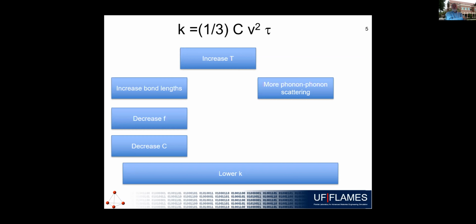Another effect is you have more phonon scattering. That is equivalent to having more people carrying cups of coffee around the room, and they're interacting with each other, so they're effectively all slowed down. When you have more phonon scattering, that's a decrease in the phonon lifetime, and that also has the effect of lowering the thermal conductivity. So these simple heuristics allow us to explain that temperature dependence in a very qualitative way.